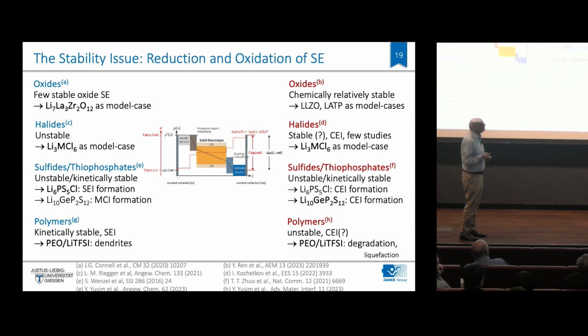What is relatively stable is one material that is a garnet-type phase, this lithium lanthanum zirconate oxide, at both sides. Halides seem to be stable at the cathode side, but all the others have their stability issues, and you have to work on that. Maybe use protecting interlayers, but this is really just an independent field of research.